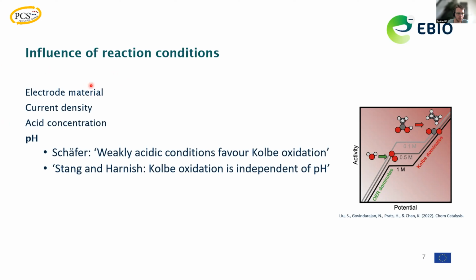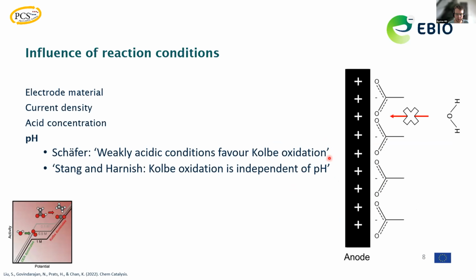But still, even though Kolbe oxidation has been known for a couple of hundred years already, the electrode materials, current densities, and also the concentration or the pH of the electrolyte are still discussed in literature. I just would like to point out that, for example, Schäfer in the earlier works pointed out that weakly acidic conditions favor Kolbe oxidation, while others are reporting that Kolbe oxidation is basically independent of pH. But the problem in all of these works is that the real product detection was not done in a way that is nowadays possible using online technologies like online GCs, for example.